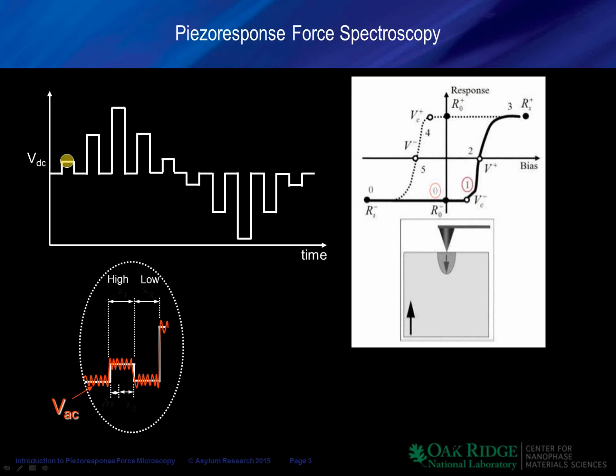If we apply a bias pulse, we will nucleate a ferroelectric domain below the tip, because by definition in ferroelectric, polarization is actually switchable, and the electric field under the tip will be extremely large compared to the macroscopic analog. So in this case, the response from this domain and the surrounding matrix partially compensate each other, so our overall PFM signal changes, and we'll see it as an inflection point in the dependence of signal on the applied voltage. If we increase the bias, our domain grows, and at some point the response from this domain and the surrounding matrix will compensate each other. So then our overall piezo response is 0, and this is what we call a coercive bias.